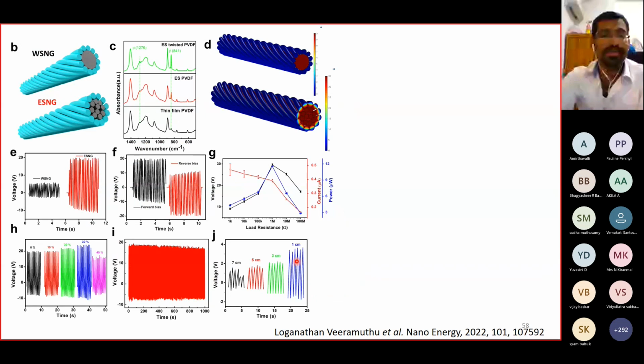Finally, we have done the demonstration for the energy harvesting devices with the help of wet spun structures and the electrospun structures. So here we can see the differences between WSNG and ESNG. The performances are quite good when compared to WSNG structures, because you can see the differences in the COMSOL simulation. Also, you can see they have very good electrical outputs, verified with real-time applications as well. Here we can see they are quite durable up to 30% strain. It can work better, but after 40%, it's getting degraded because there is some delamination or breakage in the PVDF structures.